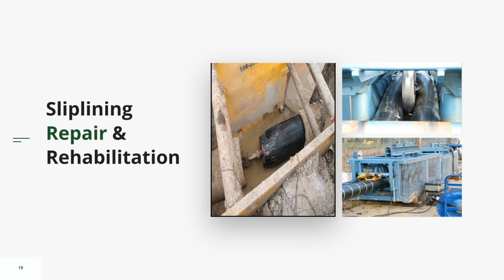Or you look at the left-hand side there, and you're slip lining. So when you slip line, you have to have a bigger annulus, and you're just slip lining this pipe through. In that case, you can see the annulus there. It's at maybe 50, 60 millimeters. So you're losing that capacity.